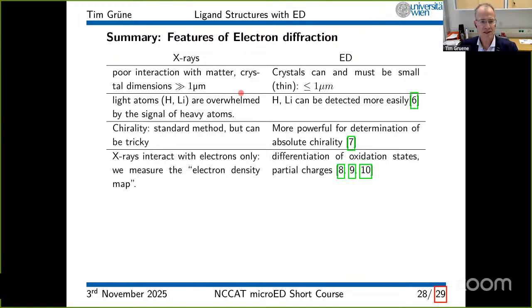With electron diffraction, crystals must at least be very thin. Remember what I said about the needles. The length of the crystal or the width is secondary, where you still tilt it, so you have a certain effect of that. But the crystals must be very thin, and there must be much, much less than 1 micrometer. I personally never measured the thickness because I don't know how to do this. Some people know how to do this. And I estimate the crystals to be 200, 300, 400 nanometers in thickness, so that they can be measured successfully with electron diffraction.